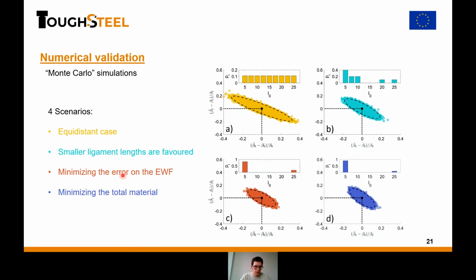And we see in red and in blue the two distributions I developed with the statistical model. We see that the spread is a bit similar for the slope, but a lot tighter for the intercept. So this is what we wanted. In the case of the values I took for this simulation, there's not a lot of difference between the two models here.